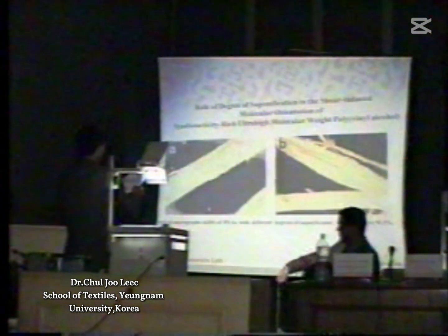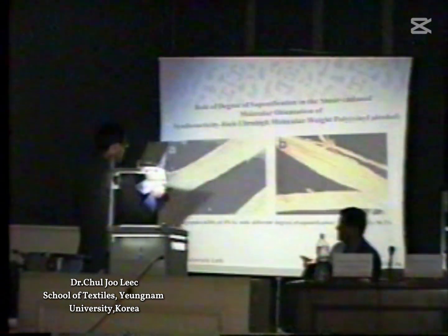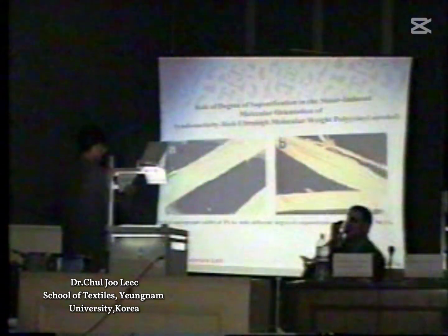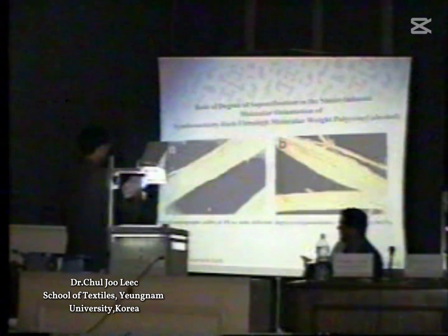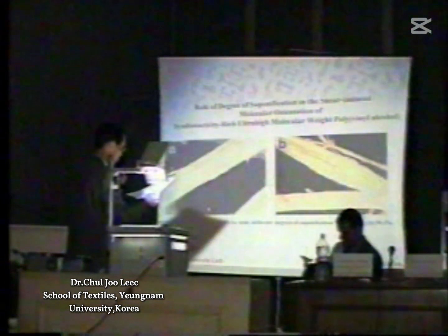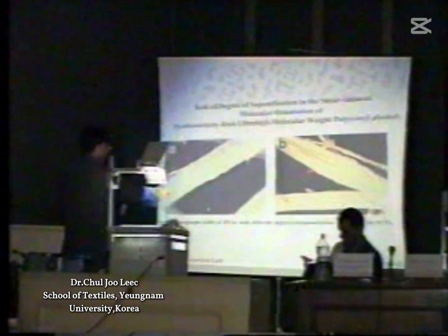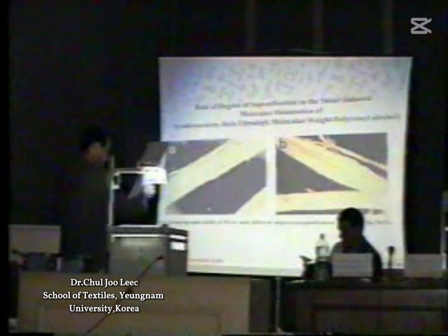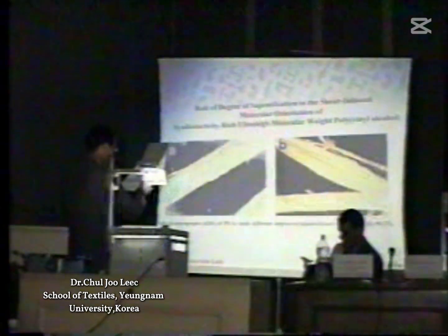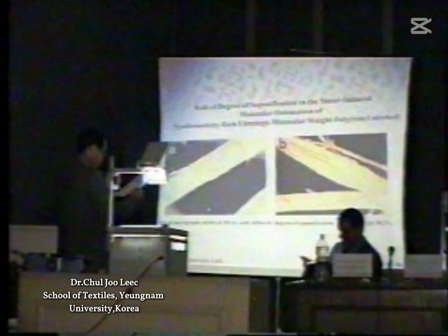From this slide, we can see the morphologies of polyvinyl alcohol fibrils having different degrees of saponification. As you see, as the degree of saponification becomes higher, the fibrils become longer and narrower. Figure A has a low degree of saponification. Furthermore, the fibrils with higher degree of saponification, in figure B, have a tensile strength of 12 grams per denier, but the tensile strength of figure A is quite low. Therefore, we tried the X-ray evaluation, and the results are in the next slide.